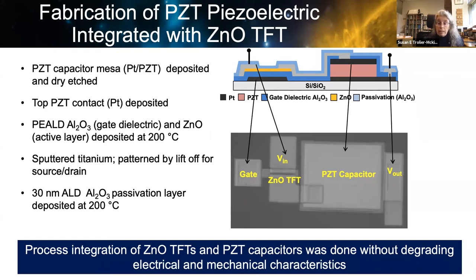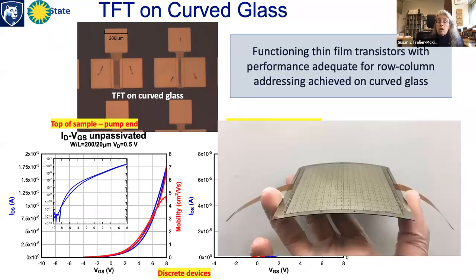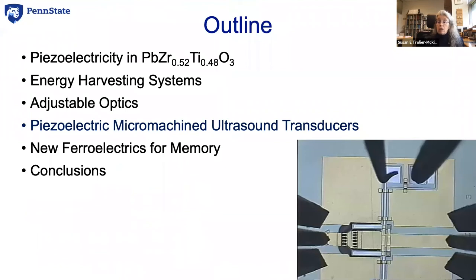We learned how to grow zinc oxide thin film transistors, very similar to those used in commercial displays, but now grown on actuator arrays — and they work. All of the electrical contacts for this entire mirror segment now run off just two thin ribbon cables. This technology is generically really appealing for many applications, including the next one: piezoelectric micromachined ultrasound transducers.